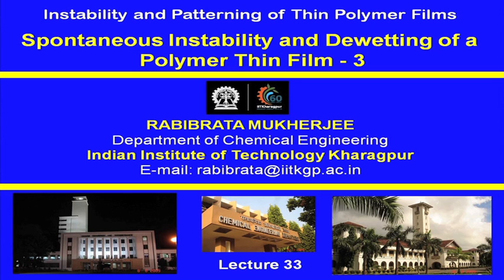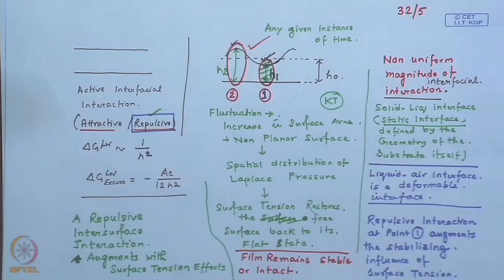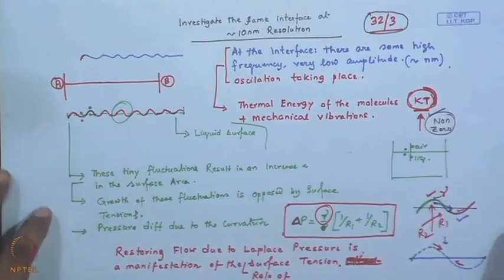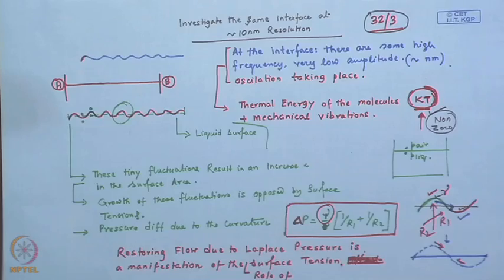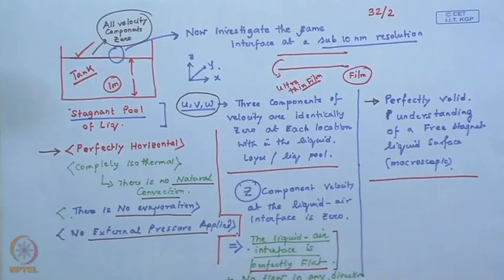Welcome back. In the previous class, we started to talk about the condition under which an ultra thin film can spontaneously become unstable with the formation of holes due to the attractive interfacial interaction between its two interfaces. So, the essential concept that we discussed is that a liquid film surface, irrespective of its thickness, has some very tiny fluctuations even if it is completely stagnant and isothermal. So, there is no temperature gradient, there is no evaporation, there is no external pressure from outside.